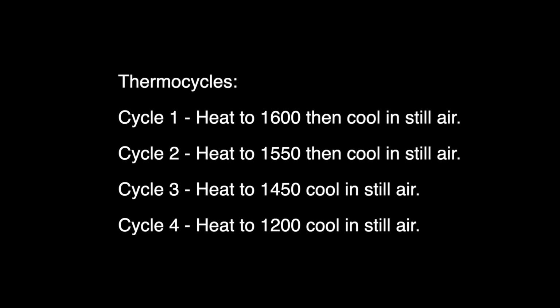Okay, so this is the thermocycling recipe we're going to be following. I was going to show every single thermocycle, but to tell you the truth, it's exactly the same thing, just at different temperatures. The first cycle, we're going to be heating it to 1600 degrees, put the knife in, bring the knife up to 1600 degrees, and then pull it out and let it cool in still air. The second cycle, we're going to bring it up to 1550 degrees and then let it cool in still air. The third cycle, same as the first two, except at 1450 degrees, and the fourth cycle, same as the first three, just at 1200 degrees.